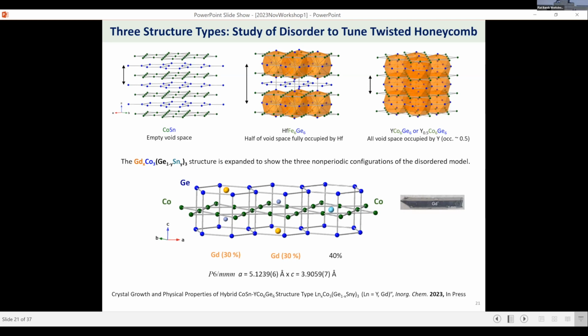But the tin is nice because it's a low melting element, and so it could help us grow big crystals. But the problem is you also have tin encapsulated in this configuration, and it's actually quite large. This is basically the cobalt tin end member, closer to that end member, and that's a 40% configuration. This is the gadolinium version. What we decided is that we have to think about the size of the rare earth, and whether it is germanium or tin.